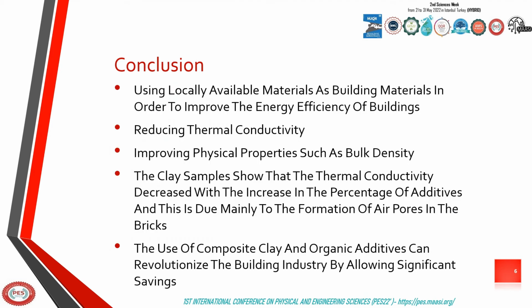The aim of this study is to use locally available materials as building materials in order to improve the energy efficiency in buildings by reducing thermal conductivity and improving physical properties such as bulk density. To analyze the impact of the percentage of biomass additives on the properties of bricks, we added 5 and 20% of biomass to the mixture of red clay. The clay samples showed that the thermal conductivity decreases with the increase in the percentage of additives, and this is due mainly to the formation of air pores in the bricks.